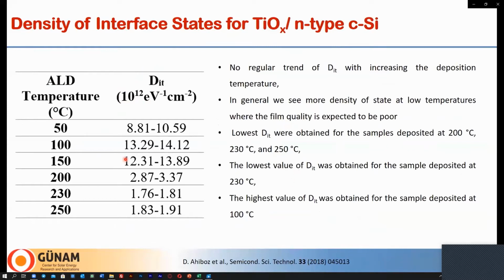As you see, they are in the order of 10^12, and this value is more or less similar to what has been reported by others in the literature. In general, we can say that we have more density of state in low temperature grown material, and less density of state at higher temperature grown. But the lowest Dit is obtained for the film deposited at 230 degrees. So these films are expected to perform better than the others in terms of density of state.